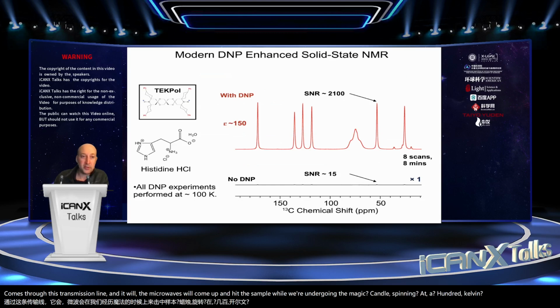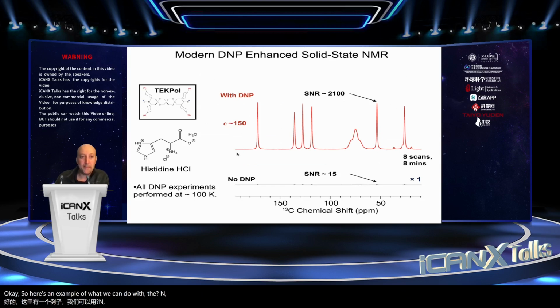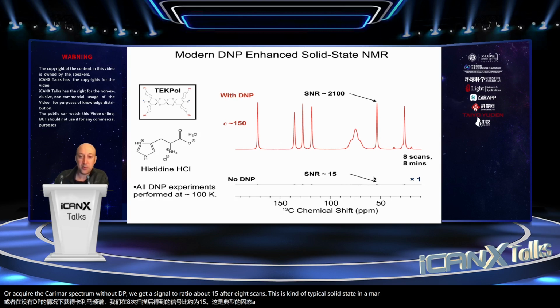Okay, so here's an example of what we can do with DNP. This is just some carbon-13 solid-state NMR spectra of histidine hydrochloride. It's a microcrystalline solid. We've had to dope it with our nitroxide biradical to do the DNP experiment. So if we acquire the carbon NMR spectrum without DNP, we get a signal-to-noise ratio of about 15 after 8 scans. This is kind of typical solid-state NMR performance for a natural abundance carbon sample.